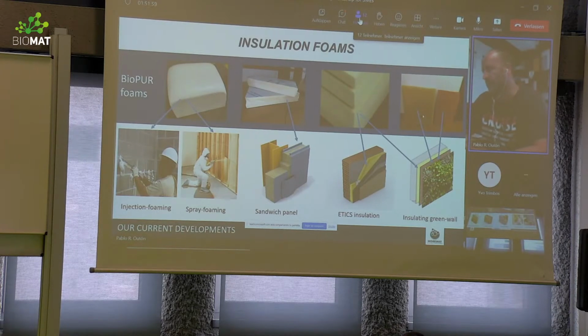We have also a new kind of foam. Well, it's not the best insulating value proposition, but it's a porous foam that allows plants to grow on top of the foam. So it retains the water and the plants can grow. It's a new type of insulating green wall that consists of 2 layers of polyurethane. One of them is porous and the other one is insulating.